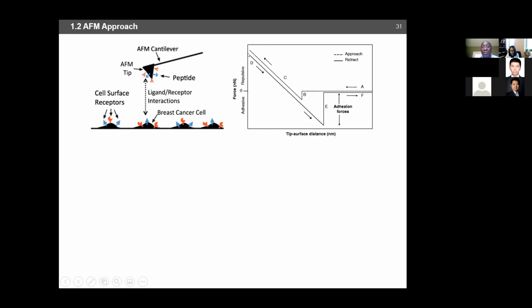You then deform it up to some level elastically, and you retract down to 0 force, but the tip doesn't detach at 0 force because of adhesive forces. So what that means is you have to load it in the other direction until the tip detaches. The pull-off force is then the adhesion force associated with this situation.